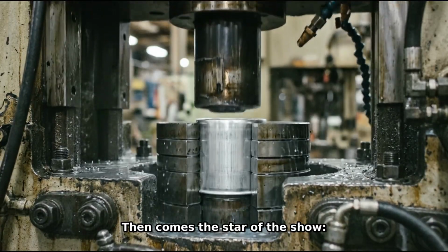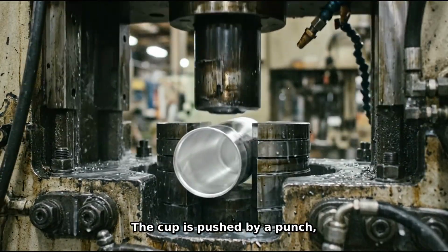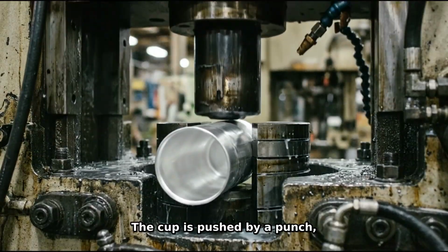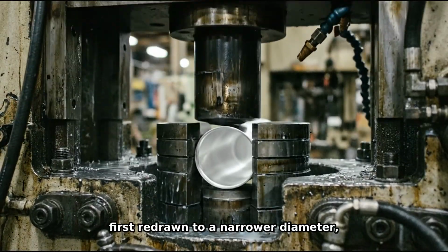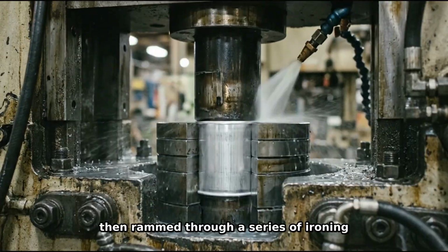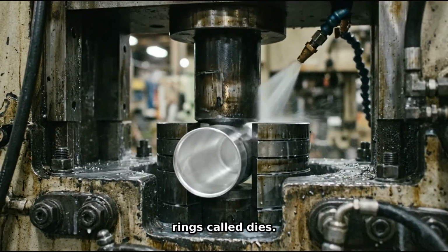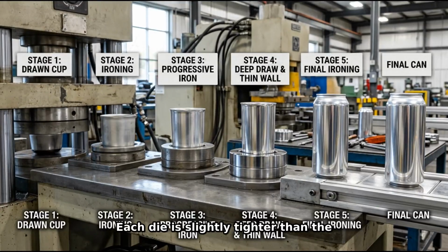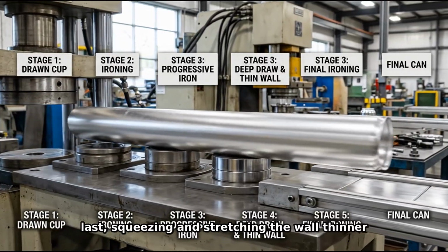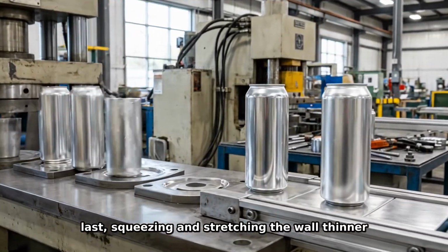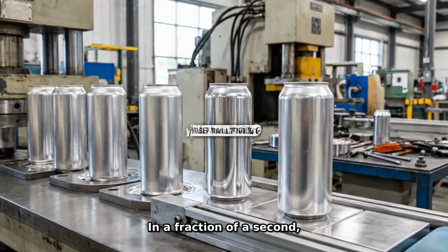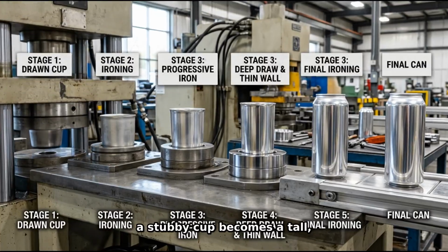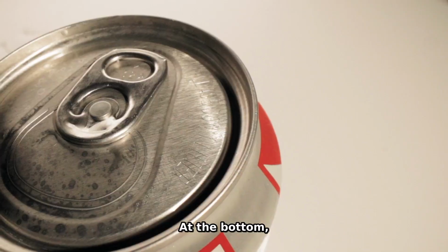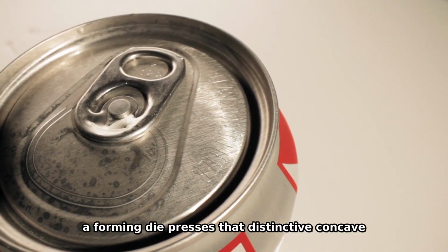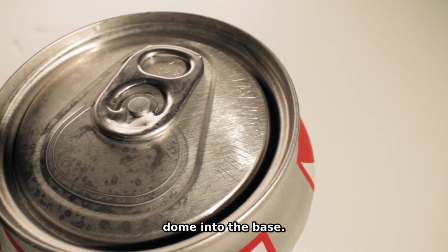Then comes the star of the show, the body maker. The cup is pushed by a punch, first redrawn to a narrower diameter, then rammed through a series of ironing rings called dies. Each die is slightly tighter than the last, squeezing and stretching the wall thinner and taller with every pass. In a fraction of a second, a stubby cup becomes a tall, thin-walled can. At the bottom, a forming die presses that distinctive concave dome into the base.